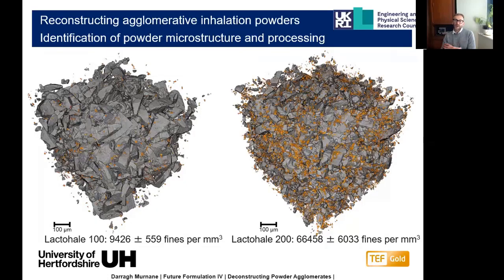So we're able to pull out multiple statistics here. We're able to identify how many fine particles are present within different types of lactose. We would be able to compare between different batches to see whether we have the same proportion of fine particles per volume. We'd be able to do things like seeing whether the distribution of those fines has changed from batch to batch. And that will allow us for the first time to start looking at performance issues and variability issues between products.